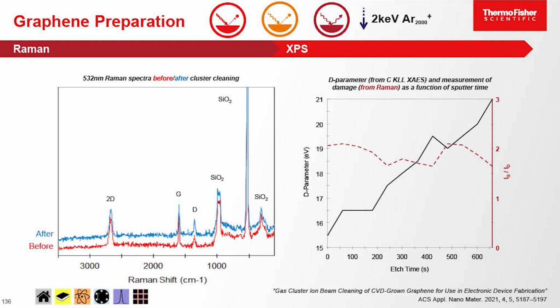So that's pretty cool, and the guys at MPL have now started working on this as a process to actually recommend for production. Cluster beams were originally developed for cleaning silicon wafers. So you have your large 12-inch wafer, and they use 10,000 atom or 20,000 atom argon clusters to just polish the surface of the wafer after doing the hydrogen fluoride etching on the wafer to clean the surface. You need something to then polish that surface to get it nice and smooth, ready to do the deposition of the chip material. And that's why the cluster ion sources were originally developed.